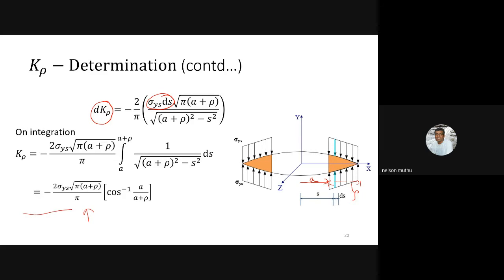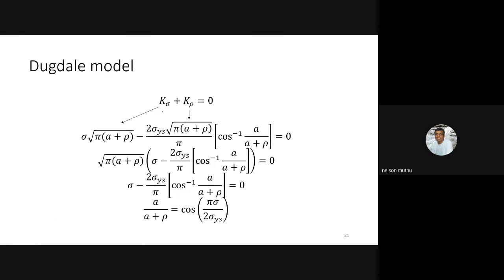So this is going to be the SIF associated with the closure stress, and we also had the SIF associated with the far field loading for a central crack of length 2A plus 2 rho. But according to Dugdale approach, even if you look at Irwin's methodology, our idea is to nullify the singularity. So that is why we have put an expression like this: K sigma plus K rho is equal to 0. When you substitute these expressions for K sigma and K rho, we are going to get an expression like this.